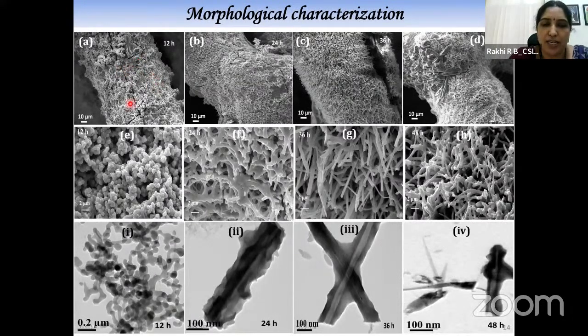After 12 hours, nanospheres are present on the surface of the nickel foam substrate. When the reaction time is increased to 24 hours, the spheres got flattened on the surface of the nickel foam, and short nanowires started to emerge at 24 hours itself. At 36 hours, we can see a brush-type morphology with perfect nanowires. Then the nanowire morphology is collapsing at 48 hours. So again, there are entangled nanowires.